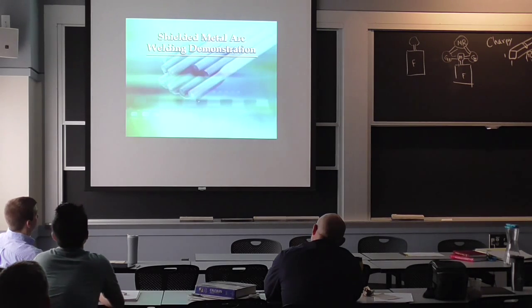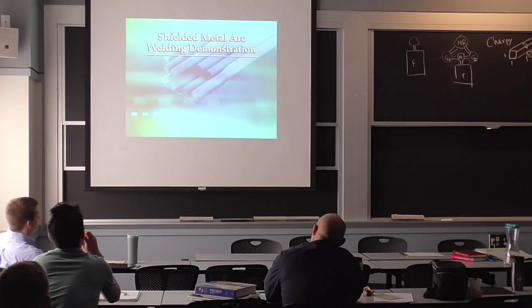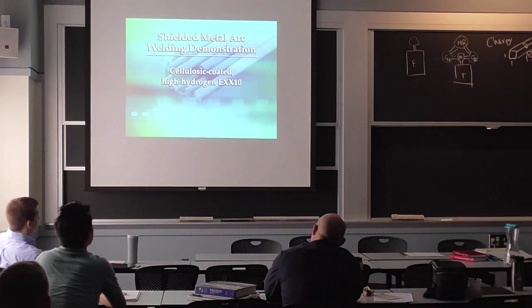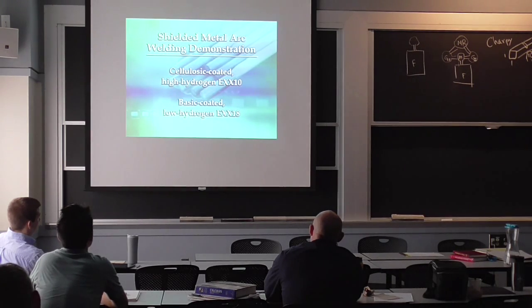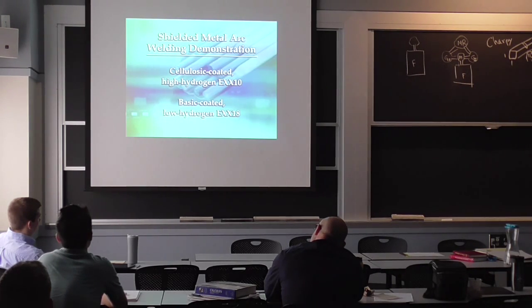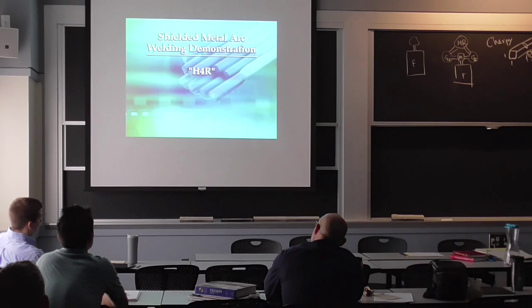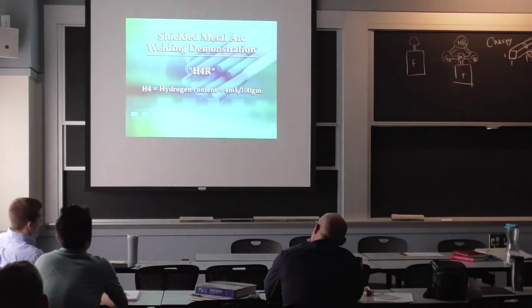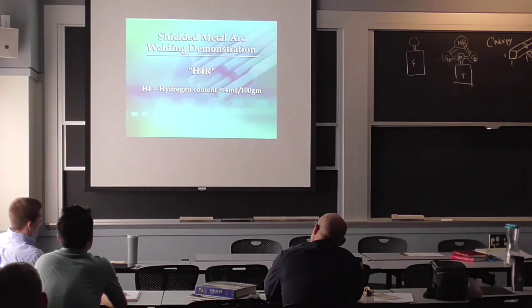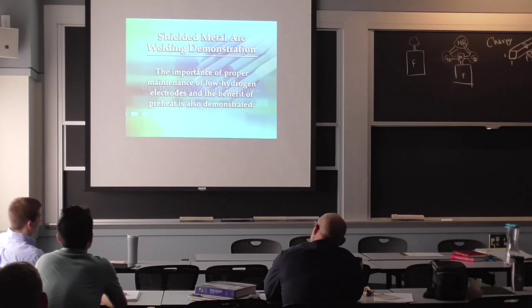The following shielded metal arc welding demonstration will show the differences between a cellulosic-coated high hydrogen EXX10 electrode and a basic coated low hydrogen EXX18 electrode. The low hydrogen electrode used has the designation H4R, meaning the hydrogen content of the as-received electrode is 4 milliliters per 100 grams or less, and it is covered with a moisture-resistant coating. The importance of proper maintenance of low hydrogen electrodes and the benefit of preheat is also demonstrated.